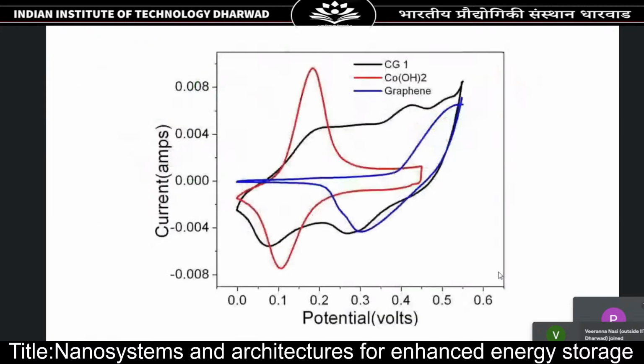So this shows the dramatic change in the area under the CV curve. You can see that the blue curve shows the graphene behavior, and the red curve shows the cobalt hydroxide behavior, and the combined behavior is shown by the black curve. So you can see that there is a synergistic interaction between cobalt hydroxide and graphene.